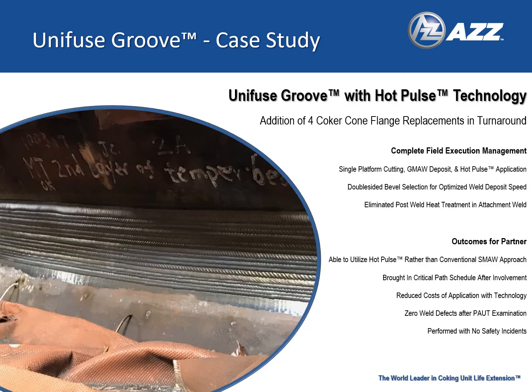During the execution of the skirt replacement process, it was discovered that the original cone to flange welds had significant cracking. AZZ was quickly able to configure their Unifuse Groove welding system to sever the existing welds and with the same setup, re-weld the components in situ. This additional scope was performed in parallel with the skirt replacement project. Completed welds were examined with linear phased array and there were zero defects. This project was completed on schedule and with no safety incidents. It's another example of AZZ technology for coker life extension.